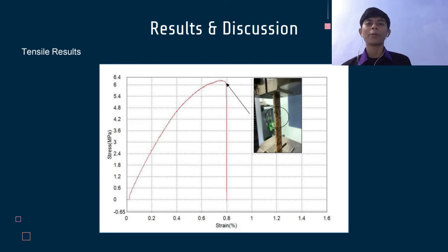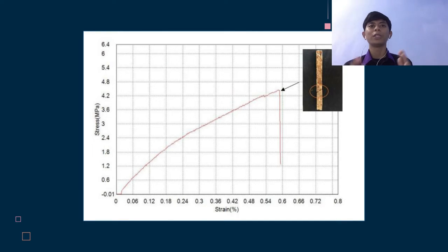So from the graph we can see that at the peak point is the highest tensile value, which is almost 6.24 megapascal, and after the peak point there is no reading, or the reading is reduced maximally because our sample is breaking down, and so the machine cannot define any reading. So we move to the next graph.